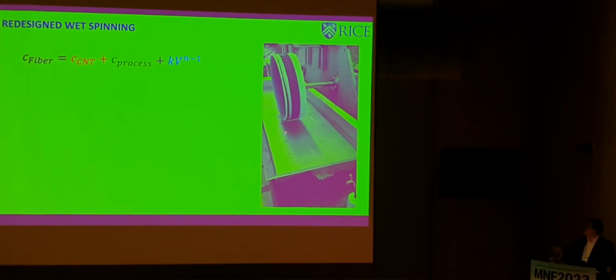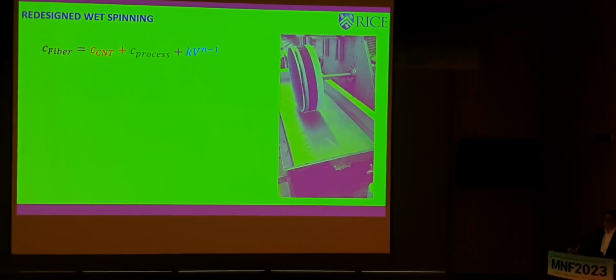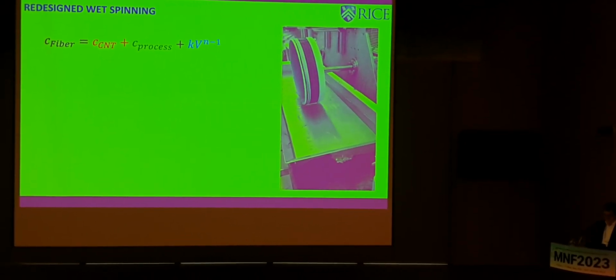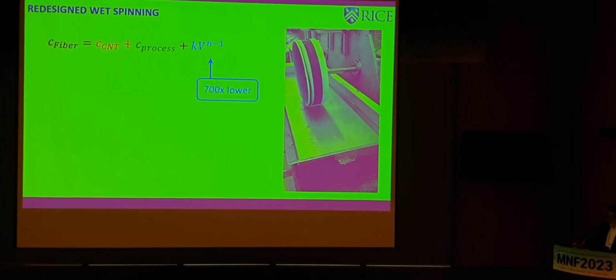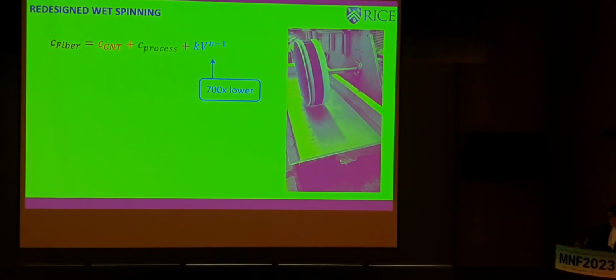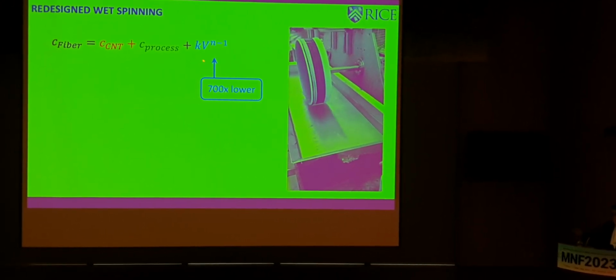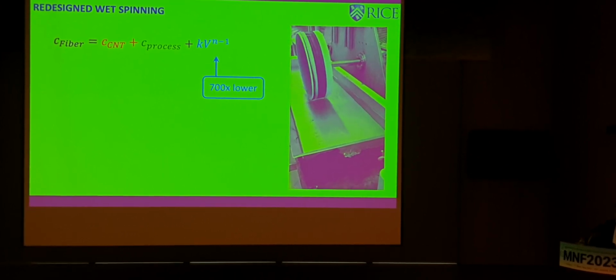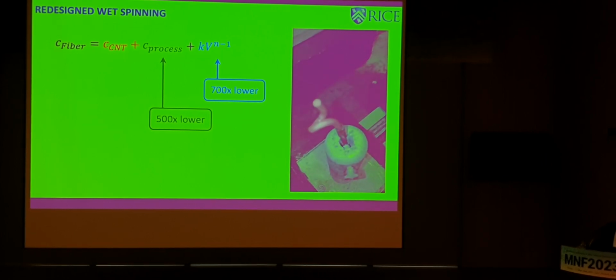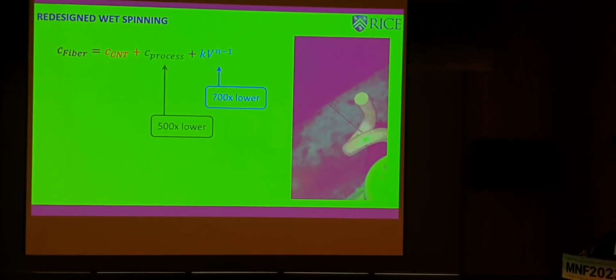Now, the other thing that we did is we redesigned wet spinning. So remember this? So that's what we do now with wet spinning. That's how fast that roll is going. What that means is that we changed the process, and I can't talk too much about it, but this kappa is now 700 times lower. And this is like 500 times lower. So this has now been intensified, and without really dropping the properties.